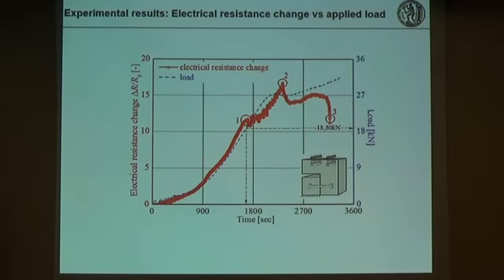up to point 2. According to previous studies, this point 1, which is at around 1,700 seconds, is the onset of microcracking. So due to the local fractures that occur inside the mortar, there is some disruption of the electrical paths, and that's why we observe this response.